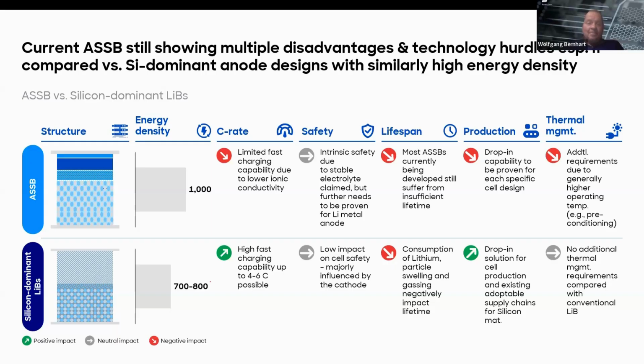On the production side, we do see very different types of designs. If you look, for example, the polymer-based approaches, they have, I would say, significantly less complex production process. So while the production looks slightly different, it can be potentially cheaper in terms of equipment. But it doesn't use in that case the already built up factories. While silicon dominant designs often are drop-in solutions, so actually what changes is only the anode material.